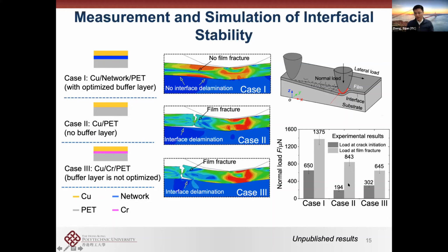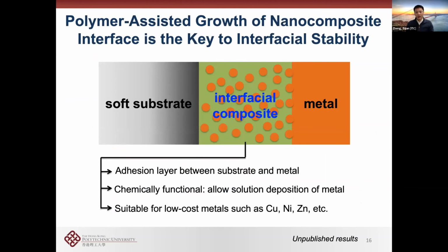But if you look at those without an interlayer, or those normally reported as thermal evaporation layer, the values are much, much worse, and therefore they form cracks much more easily or fracture much more easily, right?